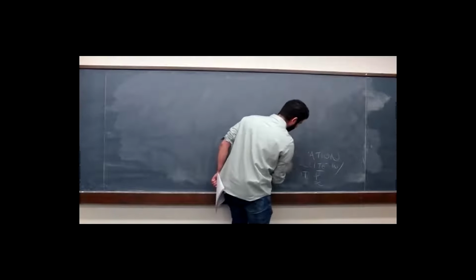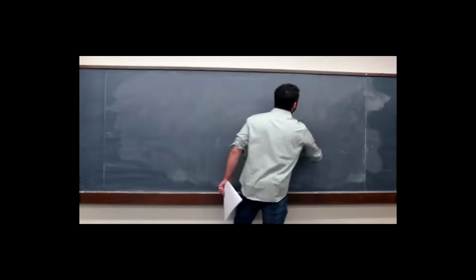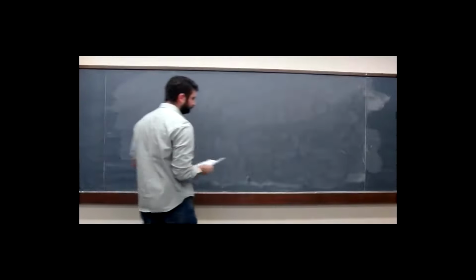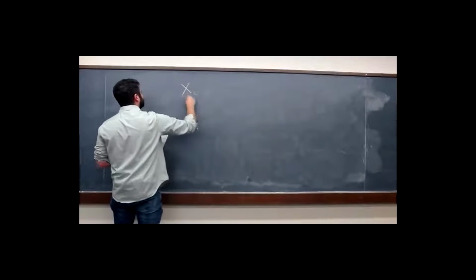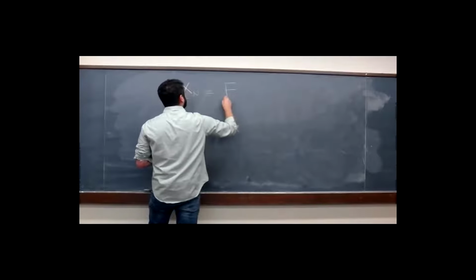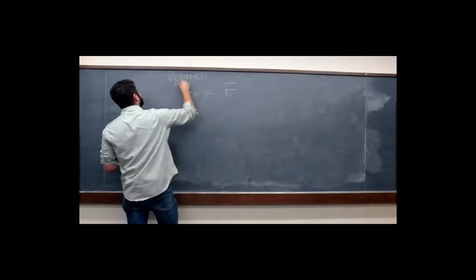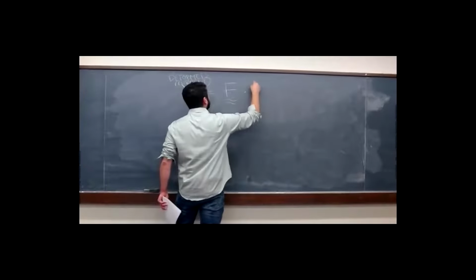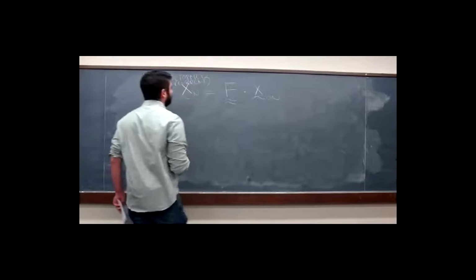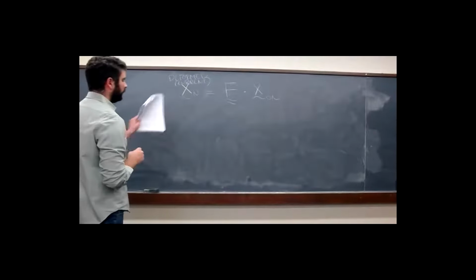So what does that mean for our lattice points? And more importantly, since we're talking about diffraction, what does deforming the real lattice do to our reciprocal lattice points? So our current lattice positions in the deformed or current state are just equal to the deformation gradient dotted with the lattice positions in the reference state.